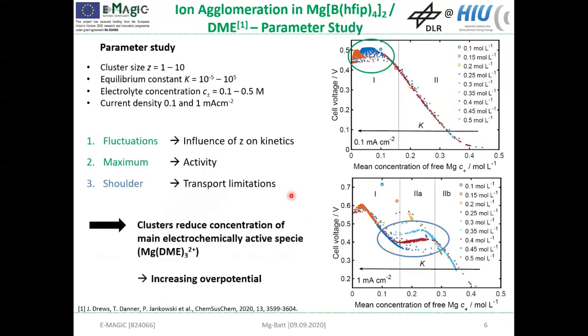But all in all, we can say that over a wide range at both current densities, we observe that the overpotential decreases when the amount of free magnesium increases. So this implies that the main effect of the clusters is that they reduce the concentration of our main electrochemically active species.